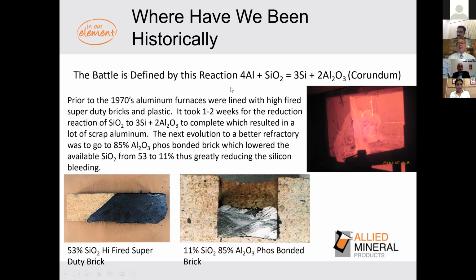So as I affectionately call it, the corundum, as you can see in this photo right here, is a furnace killer. You can see even as it grows in this corner, you start to see a separation between the lower sidewall and the upper sidewall. You can see it's starting to crack the existing refractory. It's very expansive when it goes from molten aluminum to corundum. There's a very, very large volume expansion, again destroying the refractory containment vessel.